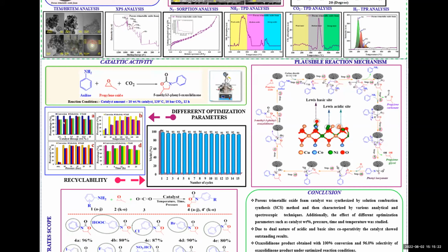In catalyst dosage, at lower catalyst dosage, the product selectivity and yield are less. When the reaction was performed at 10 weight percent, the product showed 96% of the desired product. When the catalyst dosage is increased, the product gradually decreases due to the formation of byproducts. In the effect of temperature, at lower temperature, product yield and selectivity are very low due to less energy in the reaction medium. When we perform the reaction at 120 degrees, the product showed 96% selectivity and yield. When the temperature is increased, the product gradually decreases.